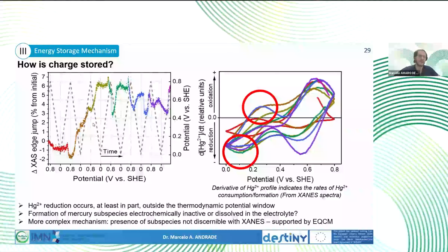Here on the left is the total mercury content. So that was basically calculated from the XAS edge jump. And we would expect the total mercury in the electrode to remain constant throughout the cyclic voltammogram. But what we have is actually an increase in the total mercury that can be seen by XAS. And then on every oxidation peak, a decrease again. So as confirmed from EQCM, that could also be seen on XAS, that mercury was mobile.